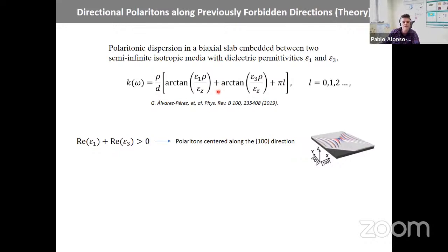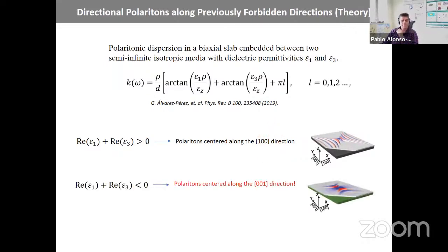We saw by studying this equation that there are two conditions that are special. When the sum of the real parts of the permittivity of the substrate and the superstrate is larger than 0, then we have the typical propagation of polaritons in these hyperbolic waves along one particular direction of the material, the 1, 0, 0 direction. But if we put the slab on a substrate in such a way that the real part of epsilon1 plus the real part of epsilon3 is negative, then the propagation of these hyperbolic polaritons was really rotated 90 degrees. So it could propagate along these directions where before they couldn't propagate, they were forbidden because the material actually was dielectric. It has no negative permittivity to support these polaritons. Now, when you put it in combination with some substrate that fulfills this condition, then you have a rotation and propagation along that direction.